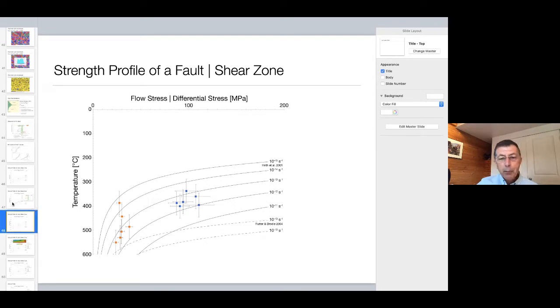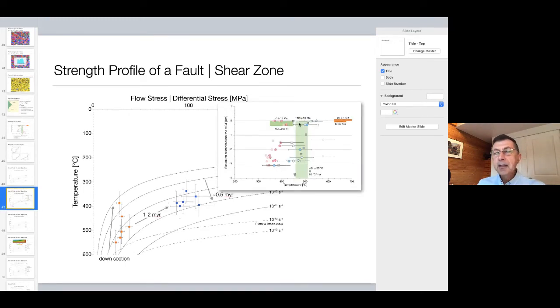However, there's a problem here. We see here that for the large grains, there is a relatively narrow range of flow stresses, 20, 30, maybe 40 megapascals, but there is a high range of strain rates, minus 12 to minus 15, which corresponds to a range of temperatures. In these diagrams, now I'm coming to the problem, I said the temperature increases with depth according to a thermal gradient, but I told you before that there is no steady state geothermal gradient. It changes with time and space. Another important thing that we saw before is that the temperature increases with the structural distance. So we have high temperatures near the MCT, lower temperatures down. And this is an inverted temperature gradient.